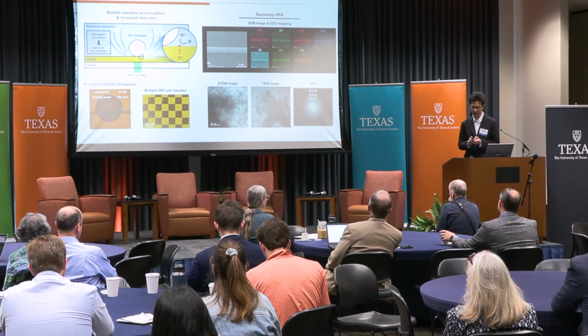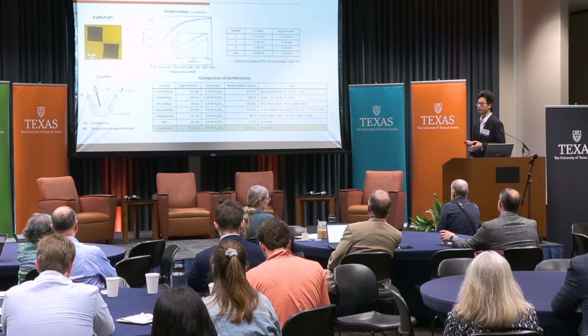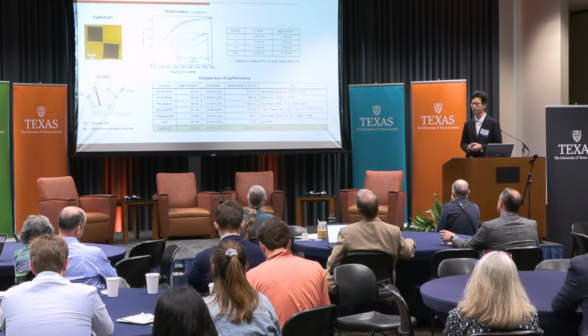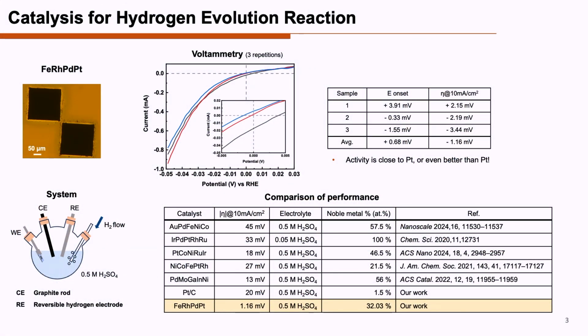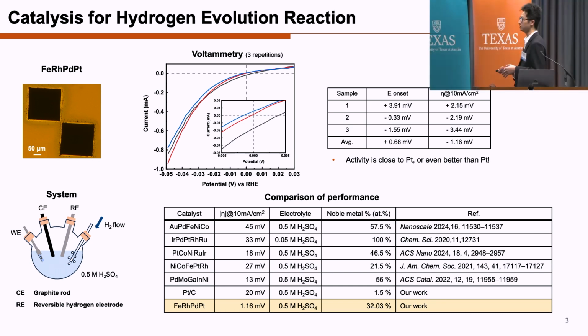Yeah. And the final part is the catalysis for the hydrogen evolution reaction. The material I use for this reaction is this, with iron, rhodium, palladium, and platinum. And this is the pattern I use for this kind of reaction. Here is the system, with a graphite rod as the counter electrode and a reversible hydrogen electrode as the reference electrode. And here's the polarization result. I did 3 repetitions from 3 different batches of this material.